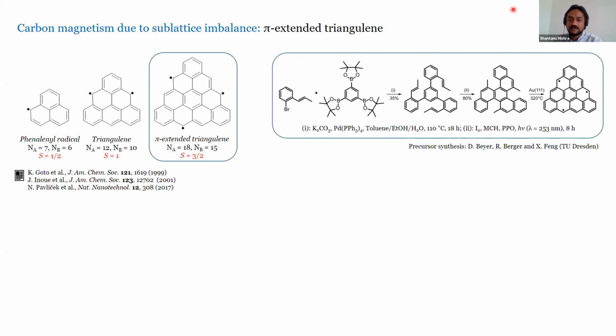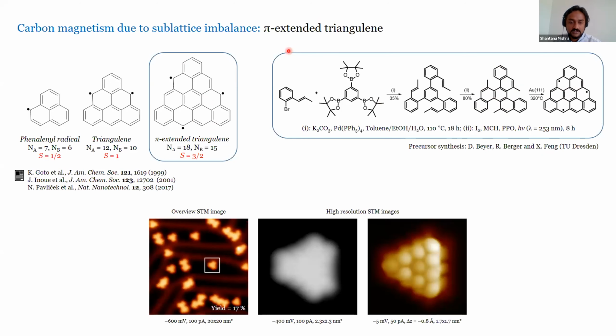So that's the way to synthesize it. We do an on-surface synthesis. That's our precursor, which is synthesized in collaboration with the group of Xinliang Feng. It's a multi-step synthesis. And then you have the final precursor, which contains these 3 methyl groups. They're expected to cyclize on the gold surface at high temperatures, and it should give you the final nanographene. And indeed, that's what happens. So here is the overview STM image. You see that the molecule is fairly reactive in the sense that the yield is only 17% or so. But if you see these 3-fold symmetric species and you take an ultra high resolution STM image with a CO tip, you see that it corresponds to triangulene.